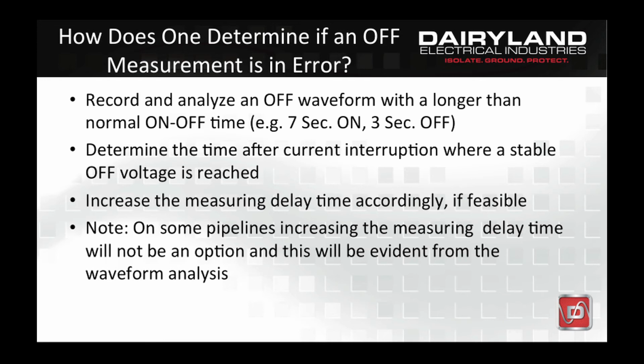For example, a waveform may show that an accurate measurement is not possible with a 250 millisecond measuring delay time, but is possible if taken with a longer measuring delay time. Measuring delay times well over 1,000 milliseconds have been used to obtain accurate measurements, but longer times can be used. When increasing the measuring delay time to obtain an accurate CP measurement is not feasible, then other means must be used to obtain an accurate potential measurement.